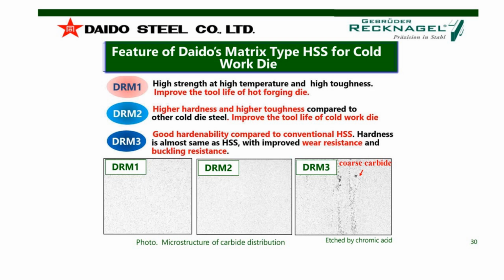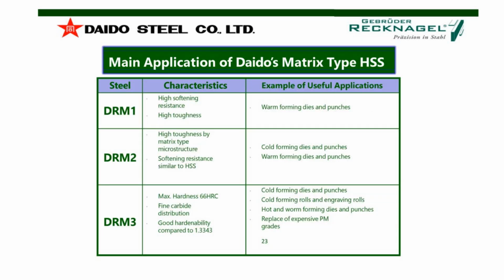Because of the ESR remelted state of the DRM series, the microstructure of the DRM series is very fine. DRM1 and DRM2 are almost free of coarse carbides, as you can see in the pictures. And because of the little bit higher content of carbon and carbide building elements with DRM3, we have some fine linings, and also single coarse carbides, but the toughness and the pressure resistance of DRM3 is much higher than with the standard M2 grade. Let's go to the next, please.